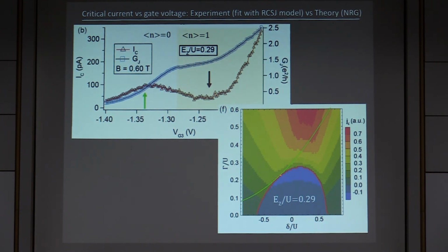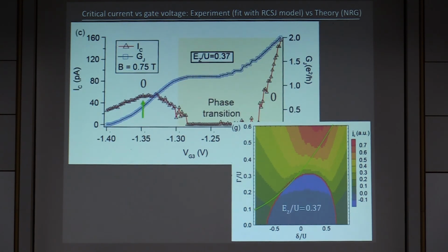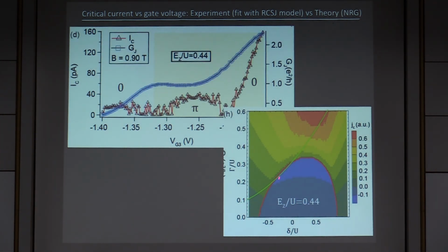Now, when we increase magnetic field, the domain associated with the doublet increases due to the Zeeman effect. And actually, our line starts to approach very much the phase boundary. And when this happens, we have a 0-pi transition. And so there, the supercurrent is strongly suppressed. And this is manifested by this suppression of the supercurrent. But if we keep increasing the magnetic field, then our line cut goes through the doublet regime, and then we enter a pi regime where we get a recovery of the supercurrent due to the pi junction effect. So we have a non-monotonic dependence with a recovery of supercurrent due to the pi effect.